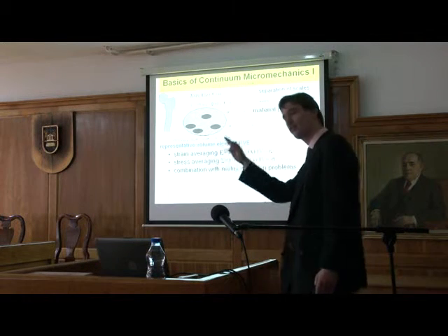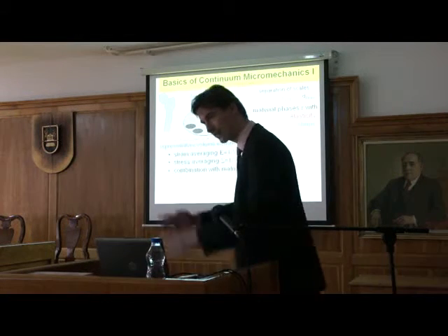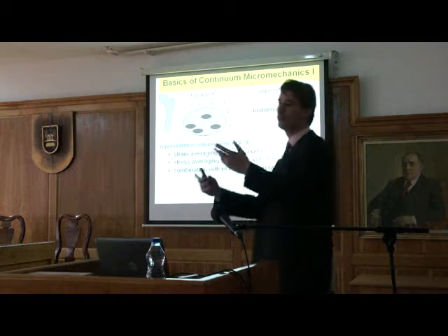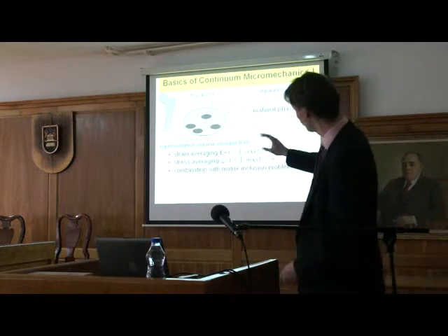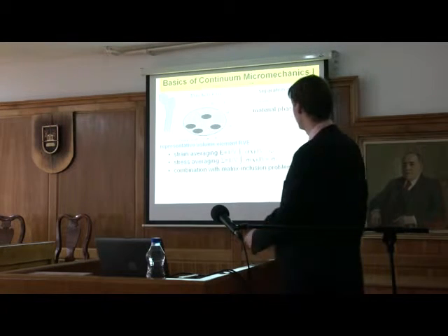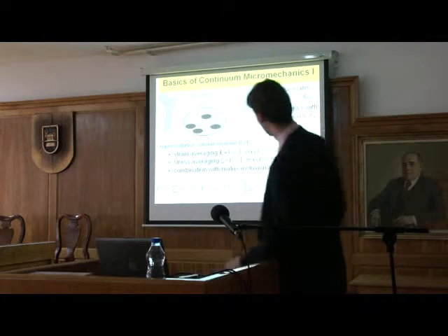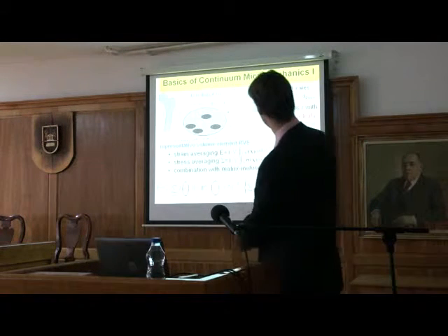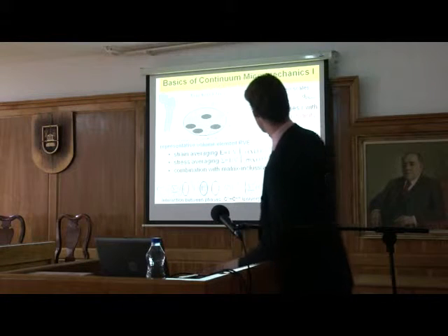It's not just a matrix inclusion problem. A matrix inclusion problem is too easy. It's correct, but you use the matrix inclusion problems as mathematical entities, like you would use finite elements for the entire structure. So you use different such matrix inclusion problems together as to fulfill, and now it's important, precisely the stress and strain average rule. And then you get this well-known formula where you have the stiffness of such a piece of material as a function of the stiffnesses of the phases and of the volume fraction and of the shape.